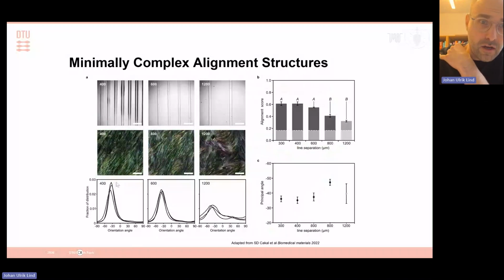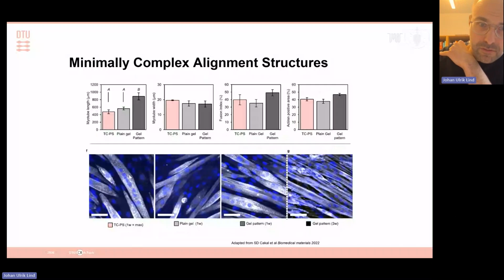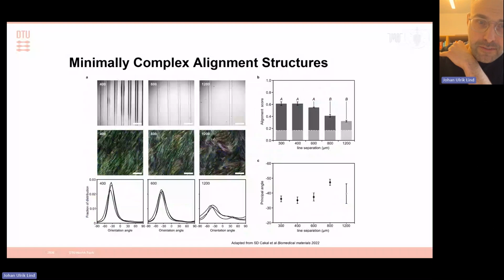And then what we found is that on these crudely patterned substrates, so 400 micrometer spacing between each line, that's about 0.5 millimeter, and relatively big filaments, we can get very universal alignment. And this obviously takes a lot less time to print than these microscopic features. So we just play with the mechanics of the material, and then we let the tissue essentially do its work. But what you can probably see here from this picture, or at least I'll show you in a bit, is that there's a little bit of an angle here, and that's an issue. Even so, maybe I should finish that point, even if you go to, say, 600 micrometers, you can still appreciate that you get a relatively good amount of control, and you only lose it if you go beyond 1 millimeter.